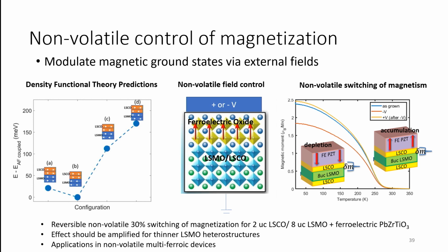So you can think of this here as a state where if you were to do a SQUID measurement, you'll be measuring the difference between the cobalt and manganese moments, whereas in this state, you're going to be measuring the sum of the moments. So if you can jump between this state and that state, you can effectively turn the material from having a very low magnetic moment to a really, really high magnetic moment, if you can do this correctly. And you also expect this state to be metallic because of something called double exchange, because of the parallel alignment of these spins.